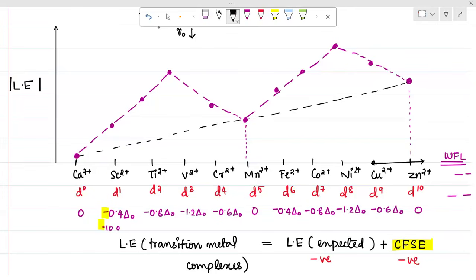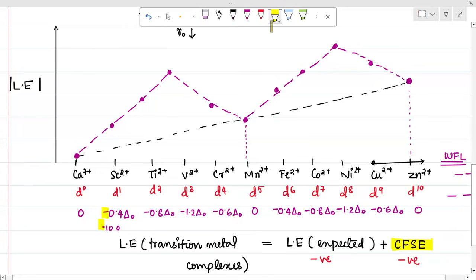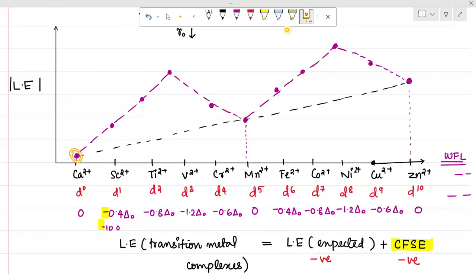Now, what we said is that lattice energy is not the only contributor. CFSE also contributes, which is also negative. So in totality, lattice energy is negative, to which you add CFSE, which is also negative. So as a whole, it becomes more negative. How much more is shown by the violet dots. So calcium, manganese, and zinc align with the expected value because CFSEs are 0. While for others, you see a trend like this, out of which the nickel complex shows the highest lattice energy. I hope you're getting it.